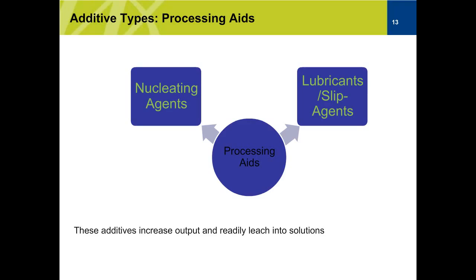Lubricant is kind of similar, and is really used to improve the flow and the processability of the polypropylene resins. So what you will see with lower quality polypropylene labwares is the manufacturers put a lot of nucleating agents, lubricants, and slip agents into their manufacturing processes, which creates a huge headache for scientists, because all of these will leach into the solution. So that's why it's very important to look for high quality labware.